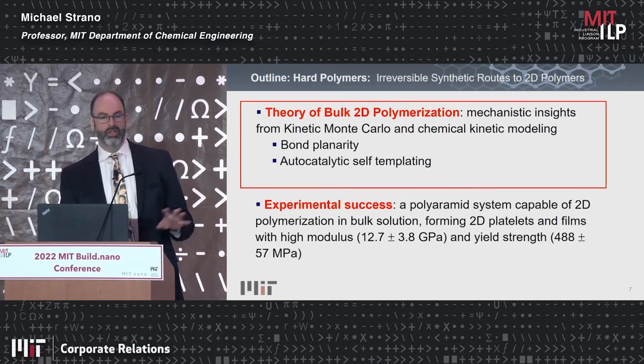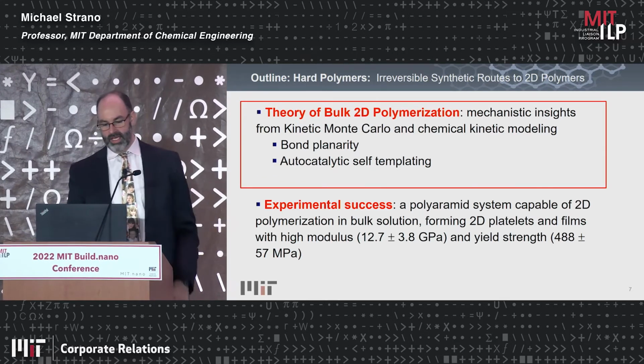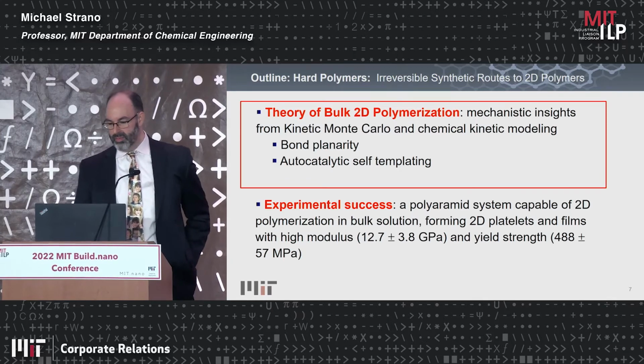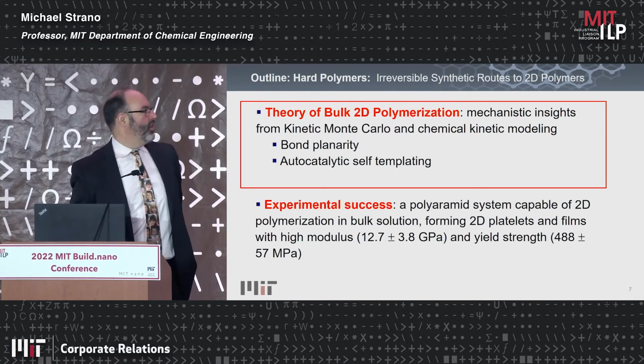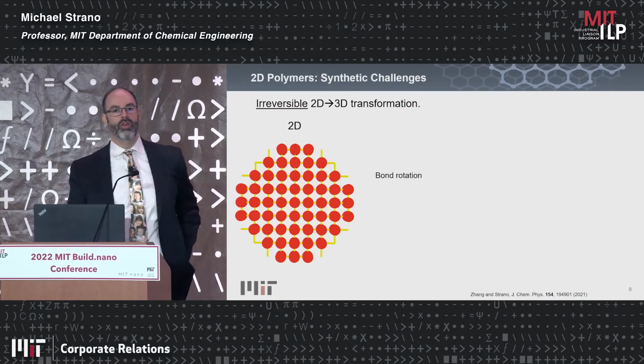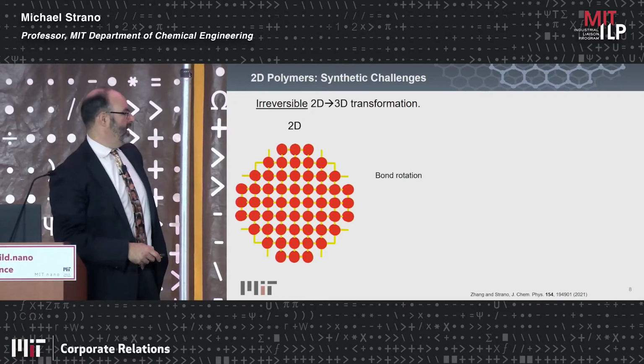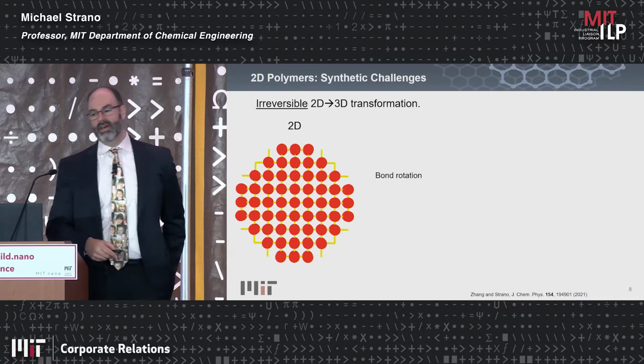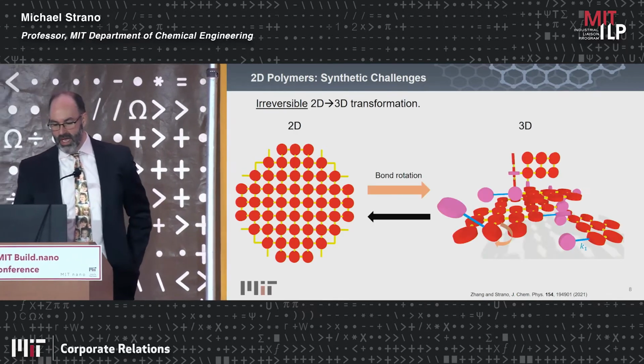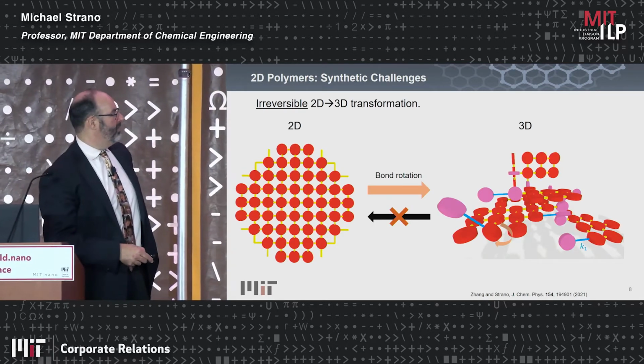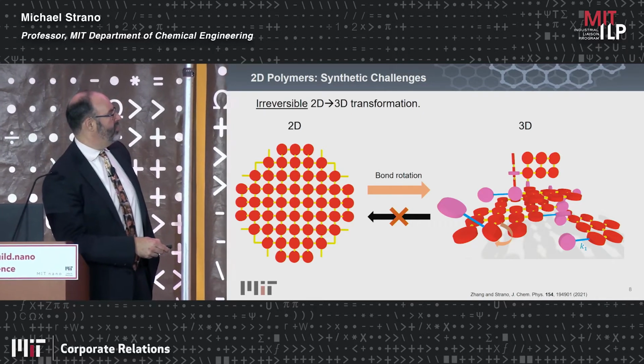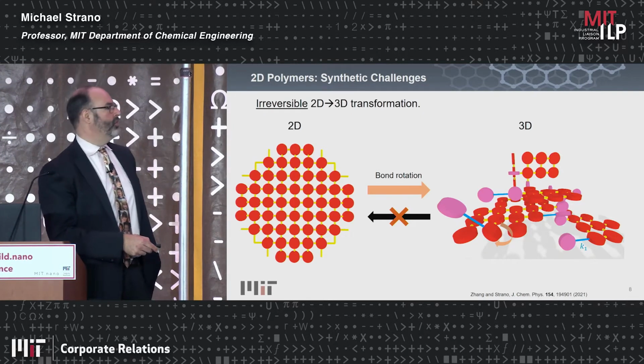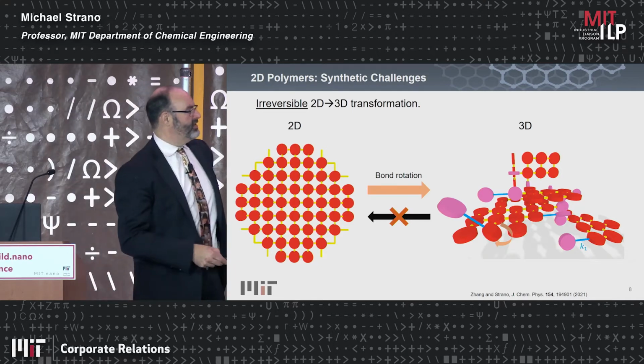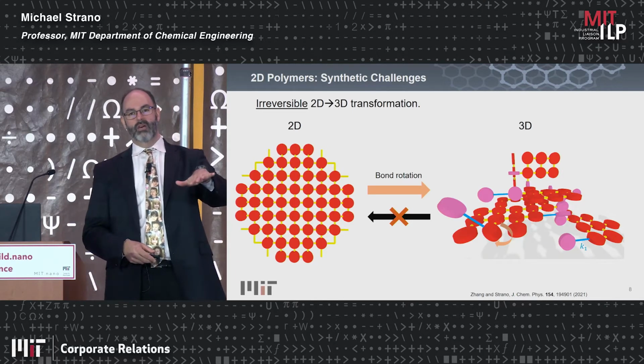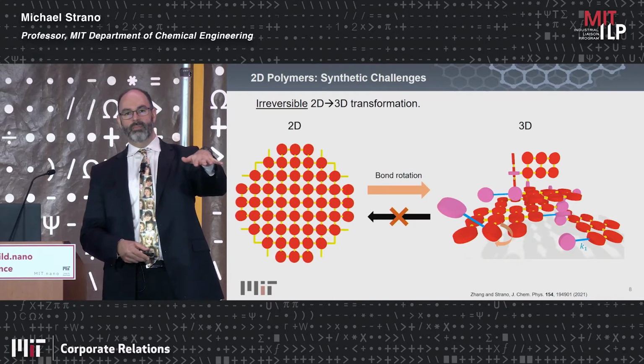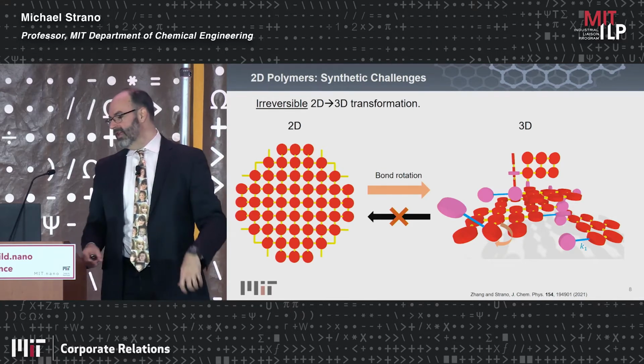Okay, so I'm going to give you the crash course in our theory of 2D bulk polymerization. So first, why is it hard to polymerize in 2D? As far as I know, we're the research group that has really codified this mathematically at different scales. Basically, if you try to grow and polymerize in a disk, so each of these disks is a little monomer, to different molecules. What happens is the system is unstable to out-of-plane rotation. As soon as a monomer rotates out of plane, you're growing in 3 dimensions.